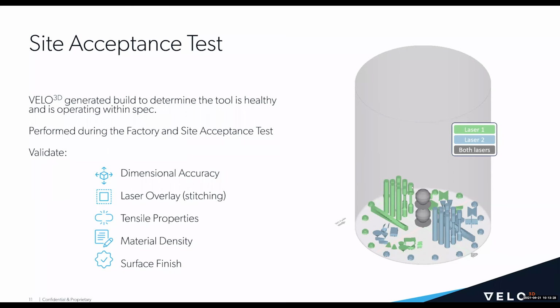Next, you have tensile properties, so you can see as-printed and as-machined tensile bars for each laser. Material density, or lack of porosity, is also verified. And then finally, surface finish is verified on several parts scattered around the build plate. This is basically the geometries that the VELO3D process engineering team has deemed the most challenging, to ensure that the tool is operating well within spec, even at some more challenging geometries.